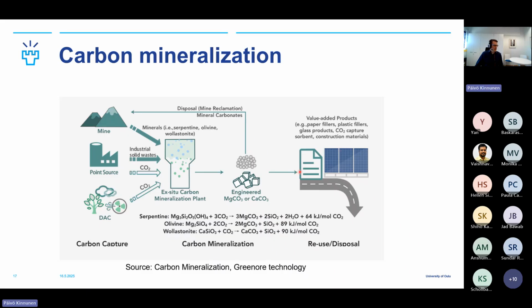So here, what essentially is done is that you have the minerals here, serpentine, olivine, or wollastonite mentioned here, or you can have industrial solid wastes, and you have CO2 from waste, or you can also have direct air capture where you get the CO2. And then what's called ex situ carbon mineralization plant, which means that you're doing that in an external process. You have also in situ mineralization, which means that you're doing that underground, and then you don't get any product out of it. You're basically pumping CO2 underground, and that reacts there to make these same minerals.